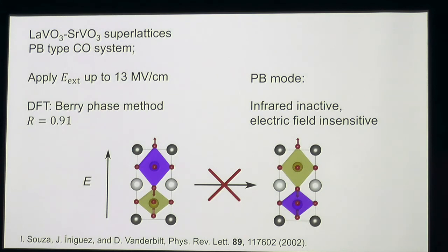Next, in DFT calculation, we apply an electric field up to 13 MV per centimeter onto the superlattice with the Berry phase method. We didn't observe any polarization flipping. We should also note that during the application of the electric field, the R ratio changes very little. This is because this polyhedral breathing mode is infrared inactive, and it does not respond to the electric field. As we mentioned before, for such an R value, it requires an electric field larger than 16 MV per centimeter. As a result, the polarization cannot flip. So far, we have demonstrated that polarization flipping under electric field cannot be achieved in polyhedral breathing type charge ordering systems.